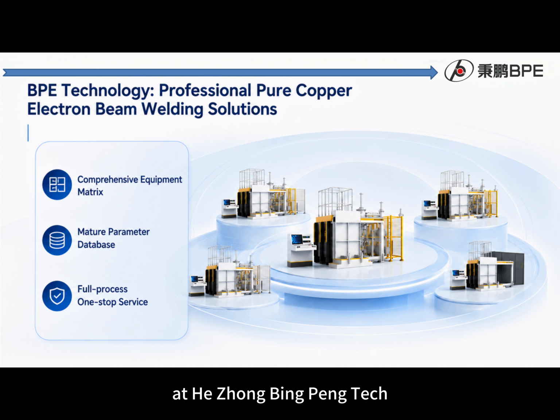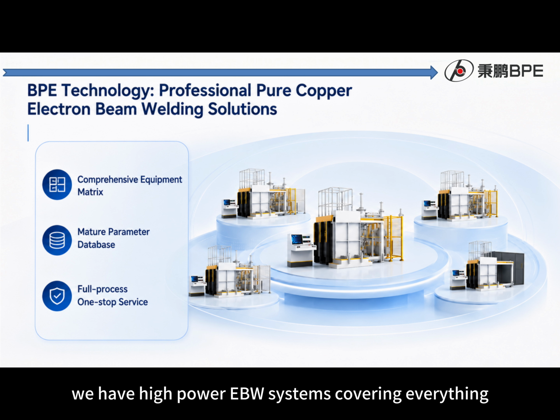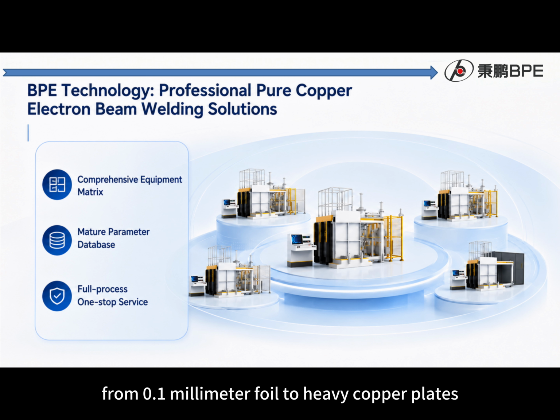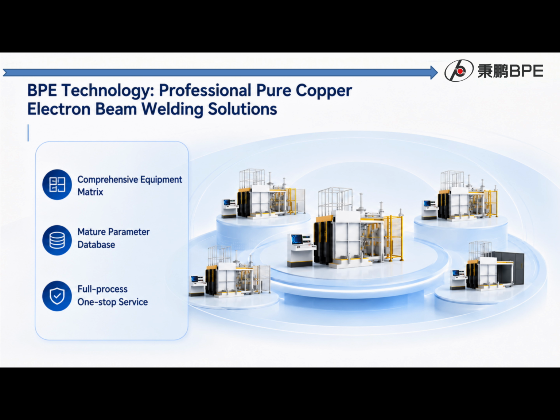At He Zhong Bing Peng Tech, we specialize in vacuum electron beam welding. We have high-power EBW systems covering everything from 0.1 mm foil to heavy copper plates. We also maintain tested, proven parameters for pure copper, brass, beryllium copper, and more. From R&D samples to mass production, we offer end-to-end certified service, backed by UT or PD testing and conductivity checks.